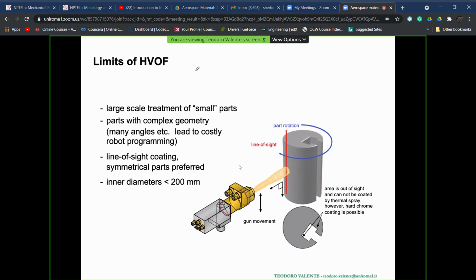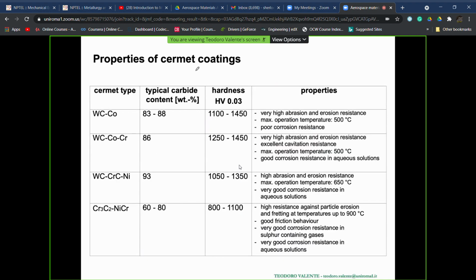Knowing the advantages as well as the limitations of HVOF, the solution which was identified was the use of cermet coatings. You see here the values of hardness which can be reached with this kind of materials, which are at least 80% in weight ceramic phase, the rest 20% in weight being the metallic phase. But this is sufficient in order to have a suitable splat during coating fabrication.